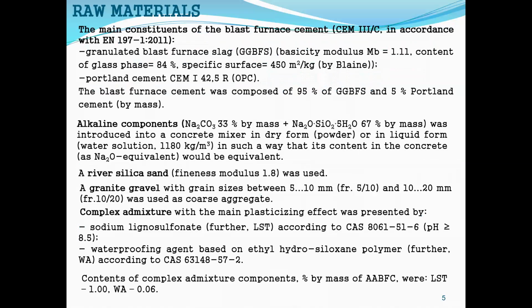The main constituents of the blast furnace cement type CEM3C were presented by granulated blast furnace slag and Portland cement type CEM1 42.5R. The blast furnace cement was composed of 95% of slag and 5% of Portland cement by mass. The alkaline component was introduced in a concrete mixer in dry form or in liquid form in such a way that its content in the concrete would be equivalent. A river silica sand and a granite gravel were used as aggregates. Alkali-activated blast furnace cement concrete was modified by complex admixtures. Complex admixture was presented by sodium lignosulfonate and waterproofing agent based on ethyl hydroxyl siloxane polymer.